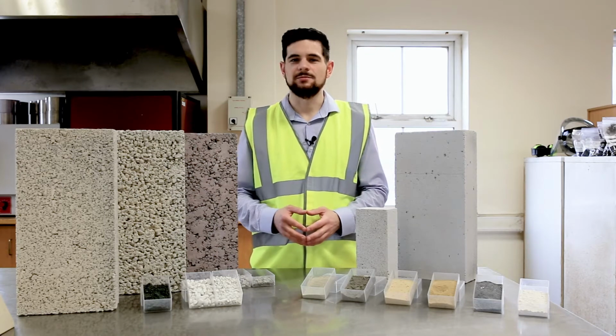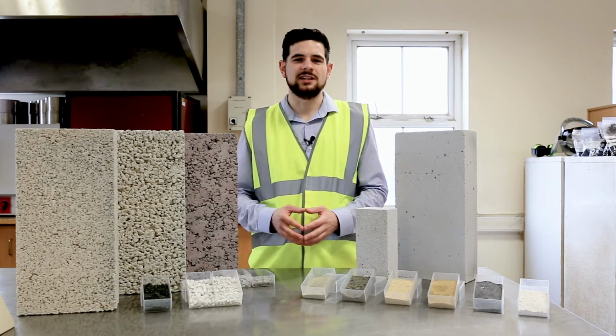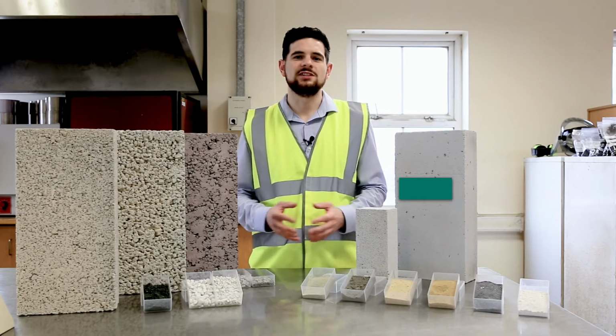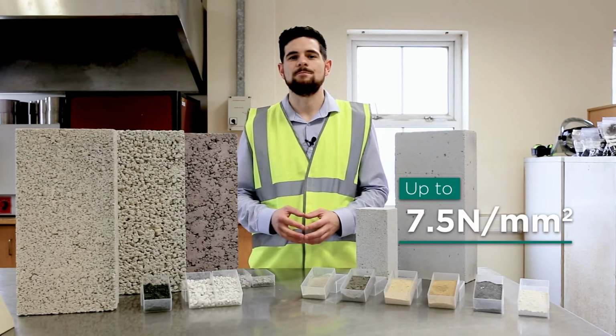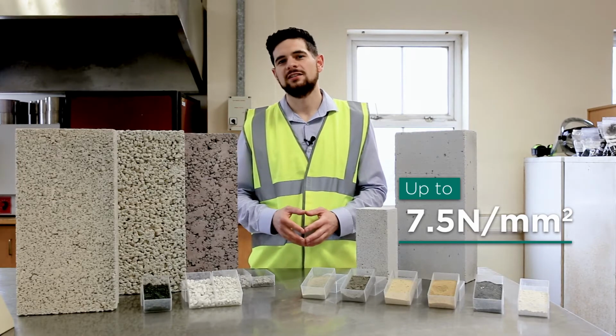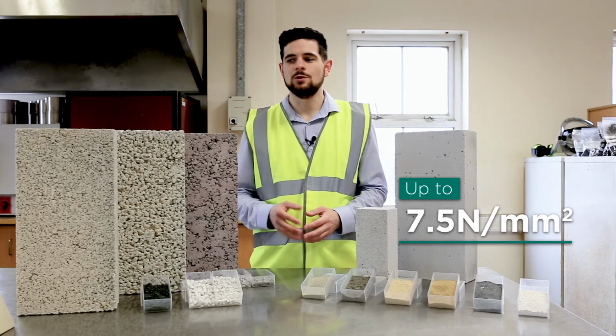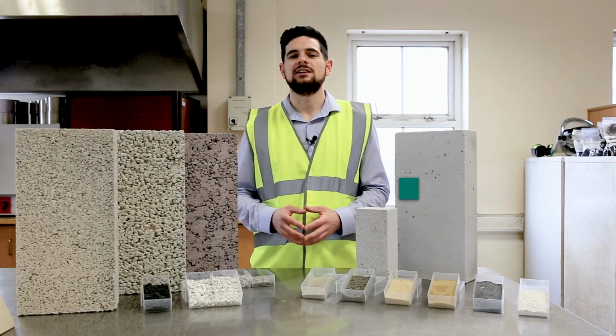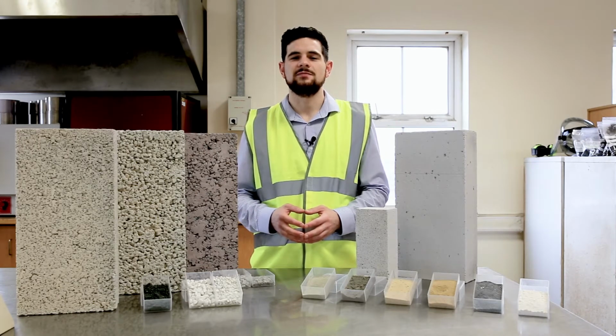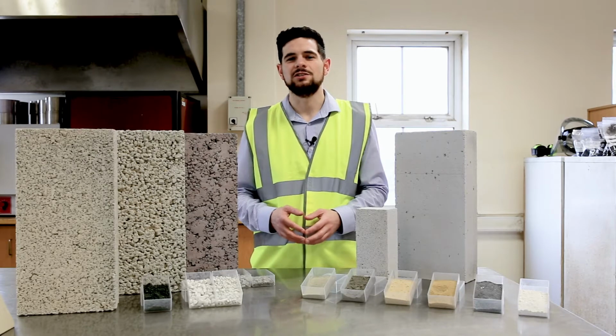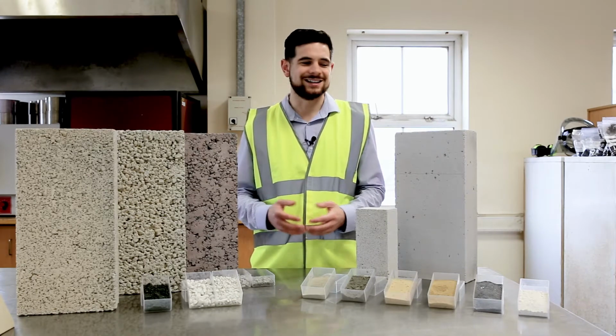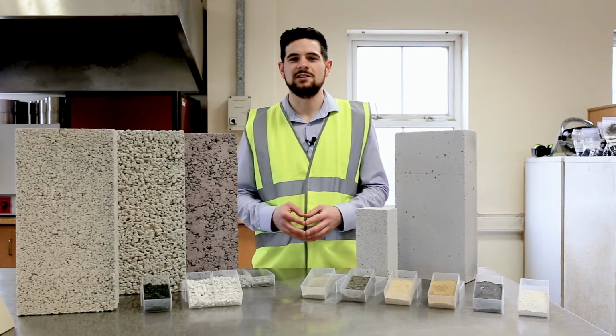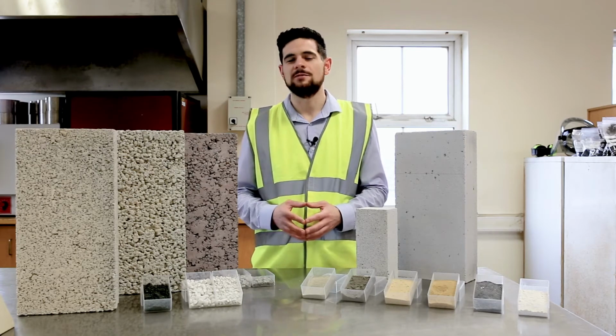Each of these blocks have the same strength, and they both meet the requirements set out in the building regulations, as they are both 7.5 newtons per millimetre squared. As they are both the same strength, some people have made the assumption that if one is specified on a plan, then it can be substituted for the other on site. But the makeup of the blocks and the manufacturing process are very different, resulting in very different thermal properties. The Quinn Lite block is vastly superior in its thermal properties, and it can achieve up to 200% better psi values than the lightweight aggregate block.